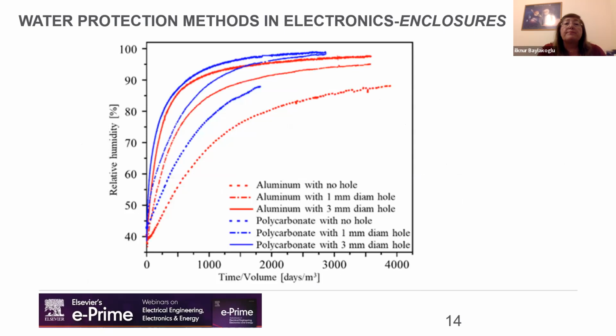And when we compare these enclosures, we can see the humidity buildup in polycarbonate, like here. Humidity buildup in polycarbonate enclosures occurs faster than in aluminum enclosures because of moisture permeation through the polycarbonate material. You can see that aluminum ones have less humidity buildup. So the enclosure selection is also critical for humidity and moisture degradation in the future.